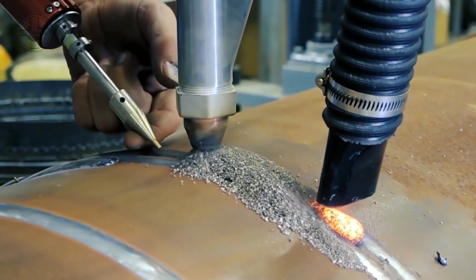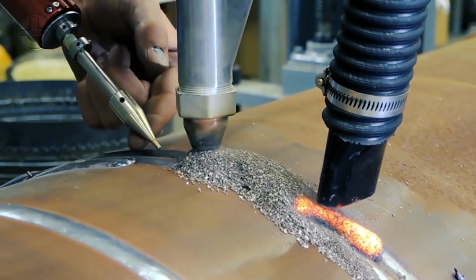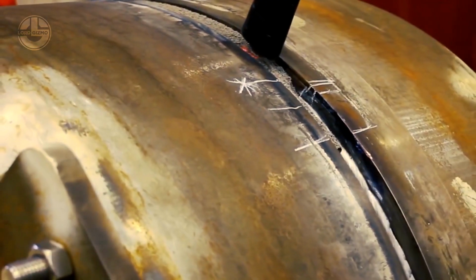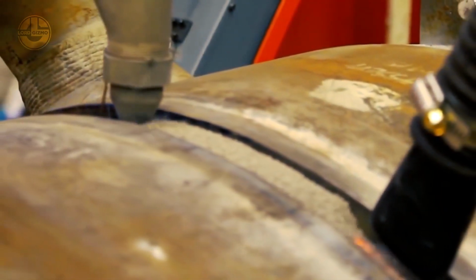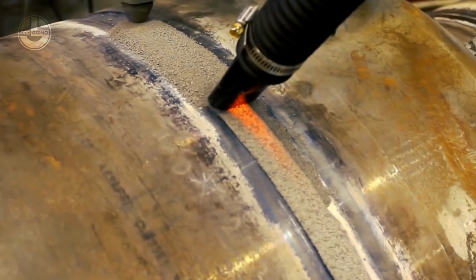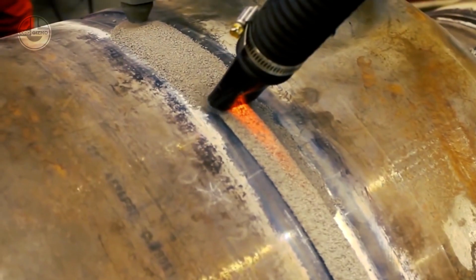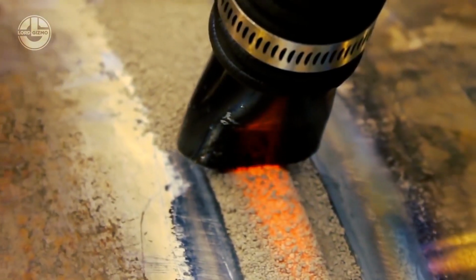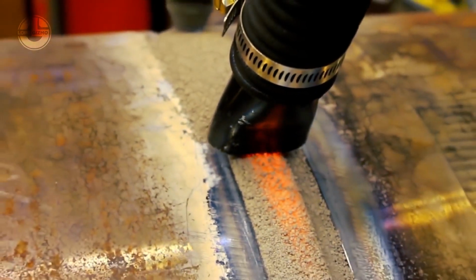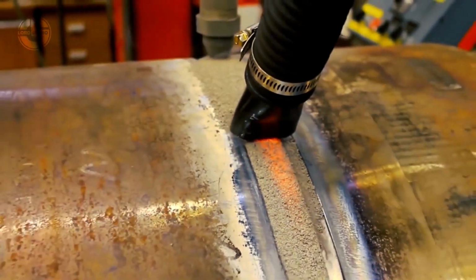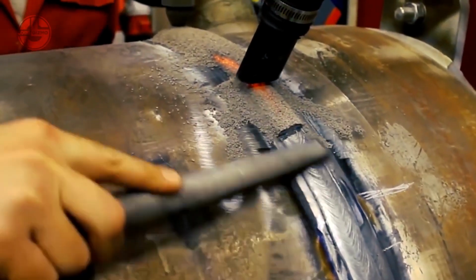Number 3. Flux. An essential part of the SAW process is the flux. It's made up of many elements like silica, lime, manganese oxide, and ferroalloys. The flux composition can be adjusted to satisfy particular needs, such as strengthening mechanical qualities, regulating the weld shape, or increasing weld penetration.